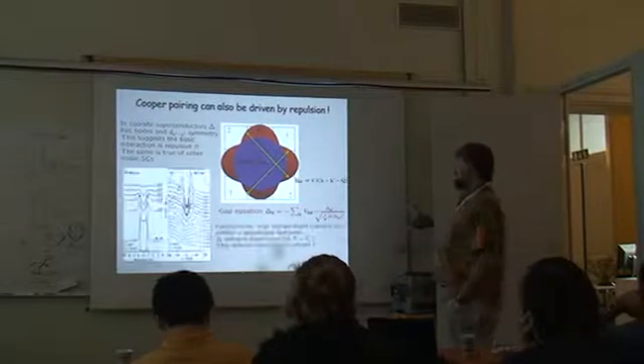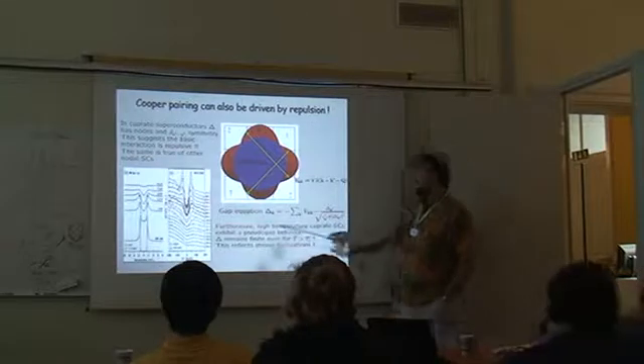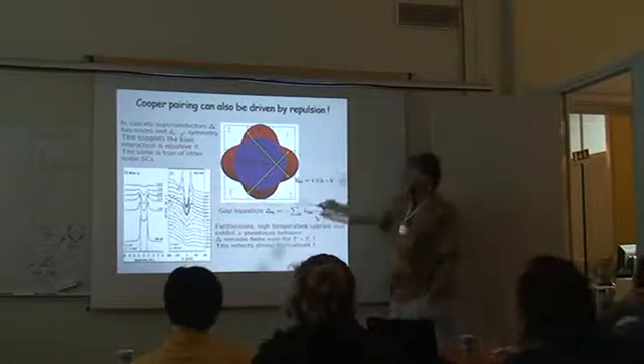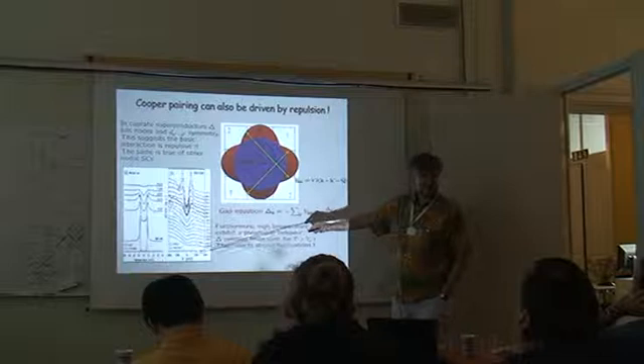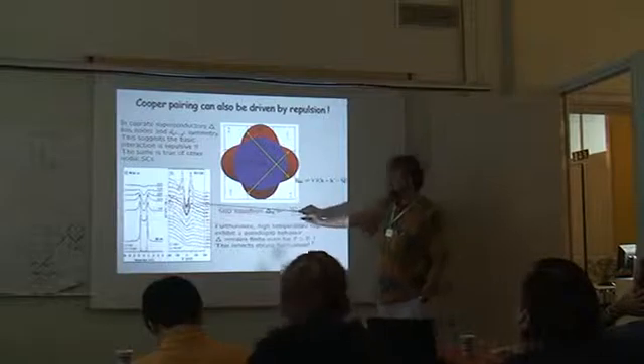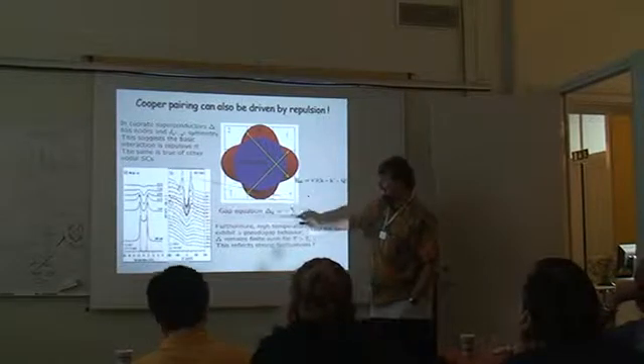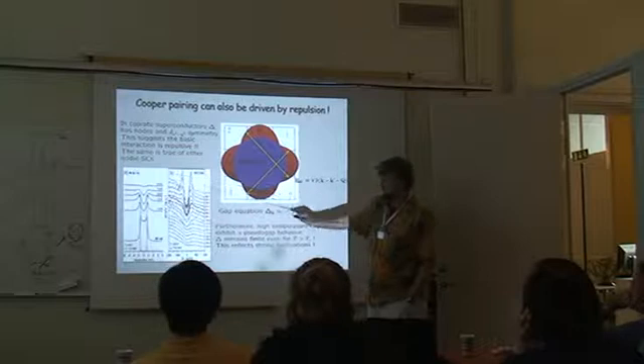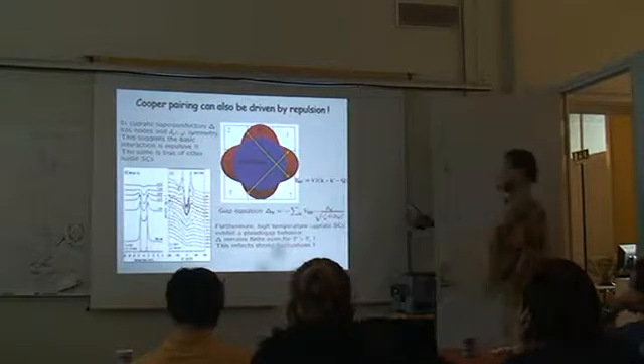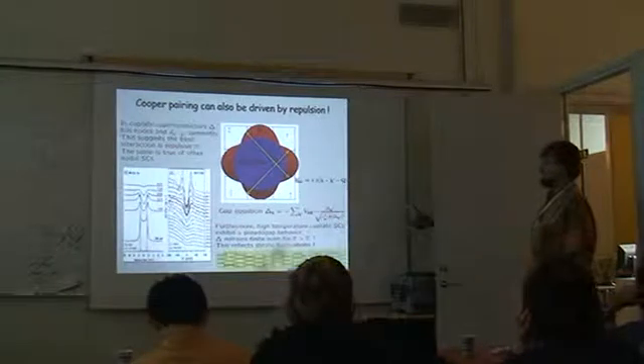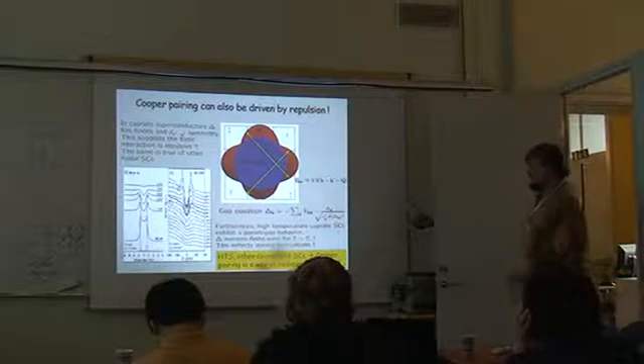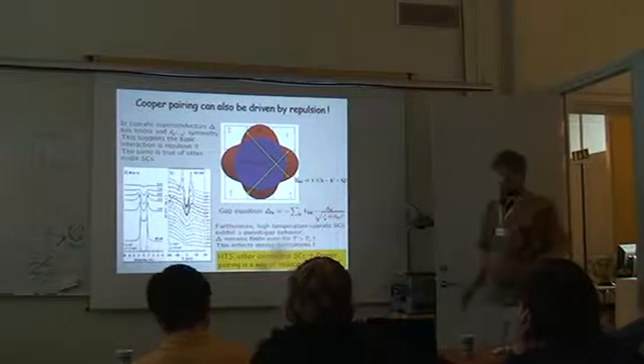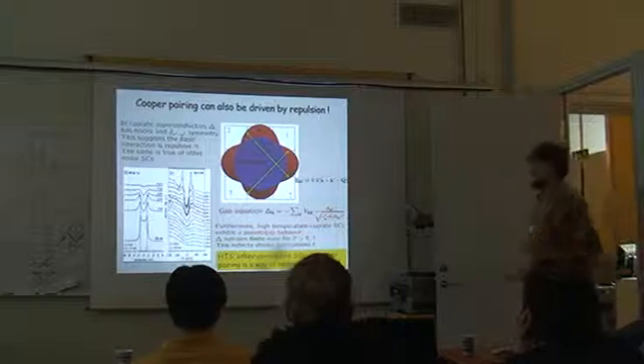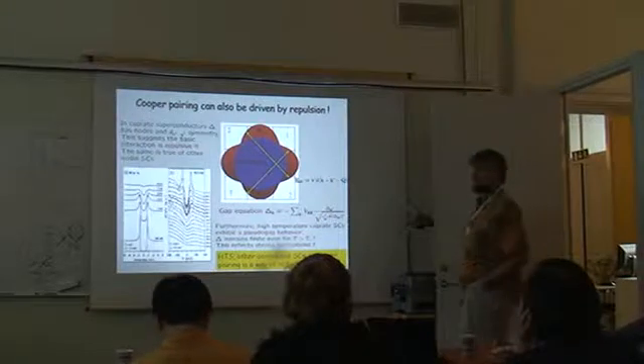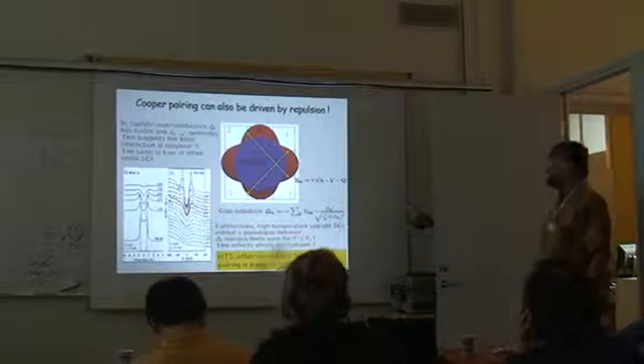Okay, so now you can get superconductivity from repulsion. Here is your pseudogap that you were asking about. This is STM data which shows here is a real TC, but the gap-like structure in cuprates seems to persist to much, much higher temperatures. And so this reflects, of course, strong fluctuations in such materials. So in correlated superconductors, we have pairing not due to attraction, but due to repulsion, allowing us to reduce this repulsion as much as we can.